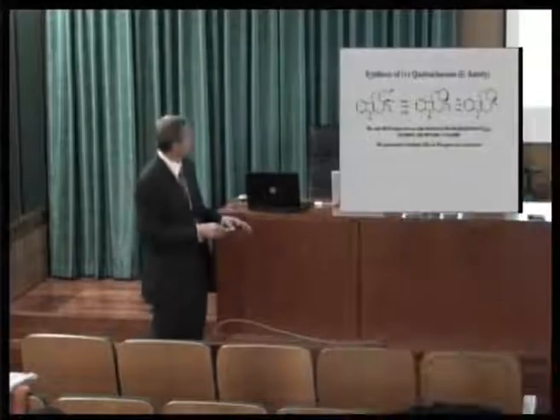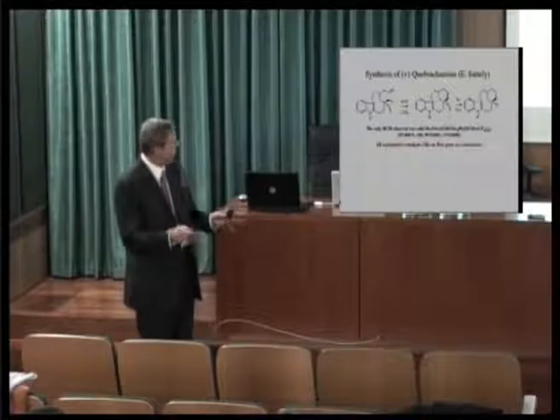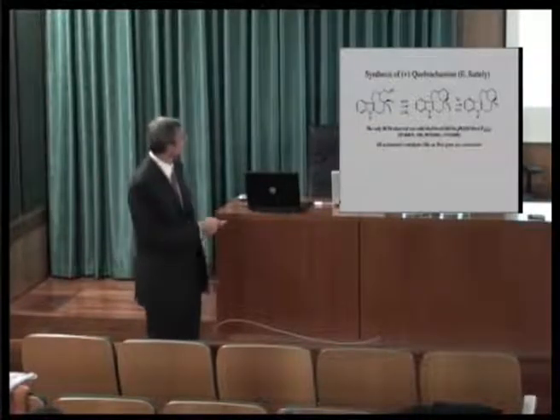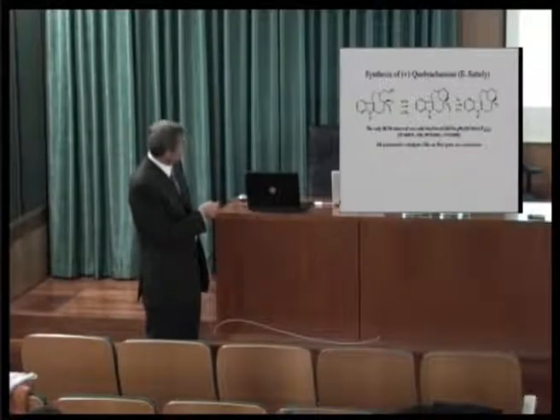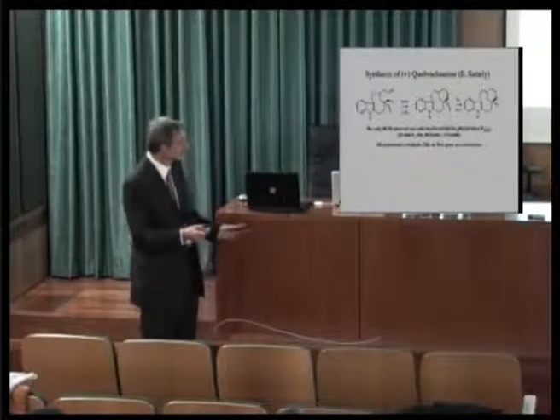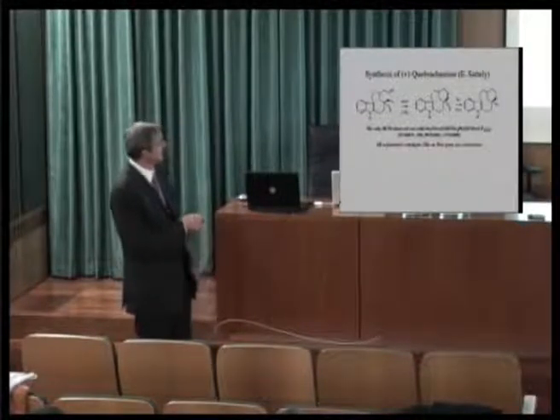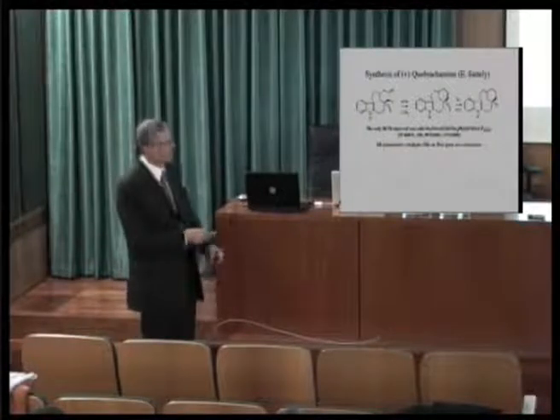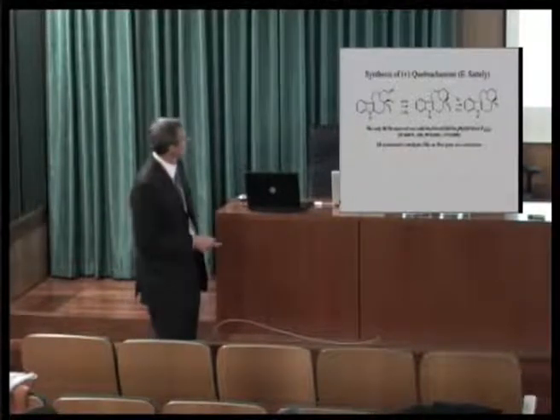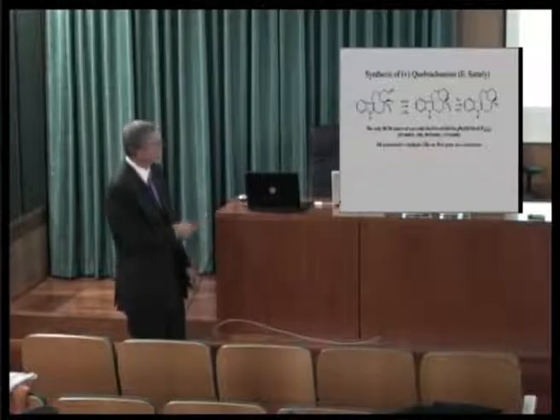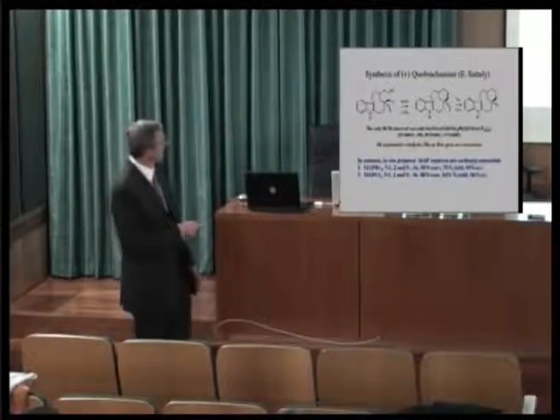conversion from here to here was never possible with any molybdenum or tungsten catalyst that we know, and no ruthenium catalyst, and there are very few of those. There was simply no conversion. But the only catalyst that worked, in fact, poorly, was this symmetric catalyst. It's not an asymmetric catalyst, not an unsymmetric catalyst. It's a bis-hexafluoro-tert-butoxide, so-called Schrock catalyst. But there are many. This is just one, and of course it's not enantioselective.